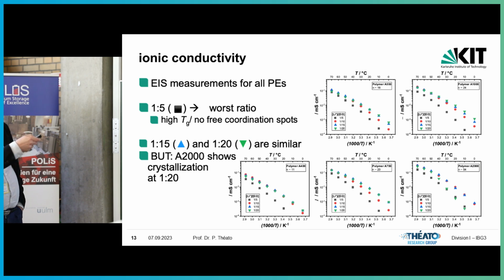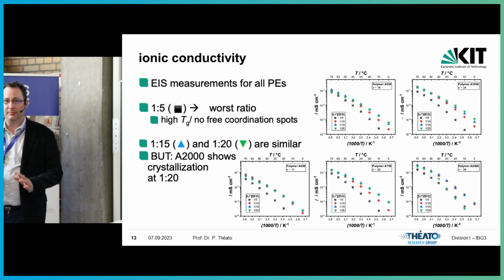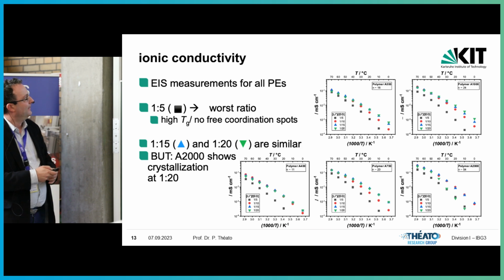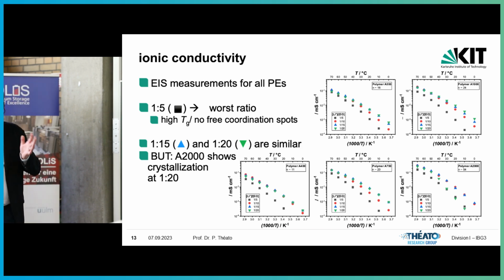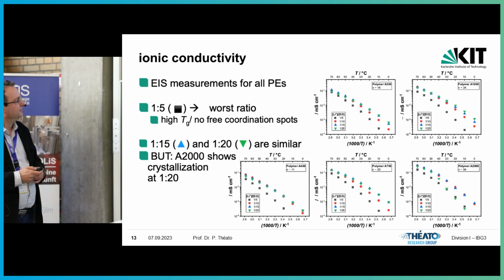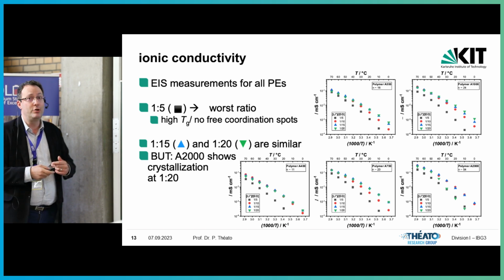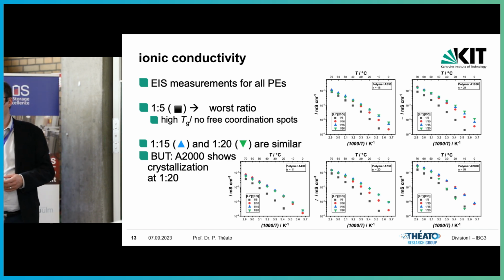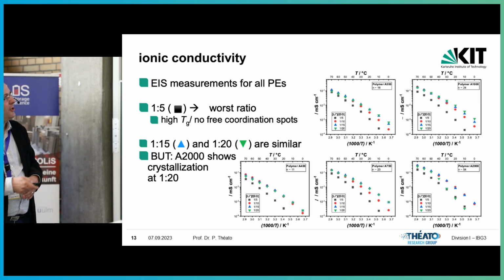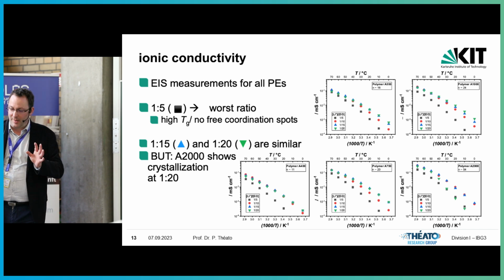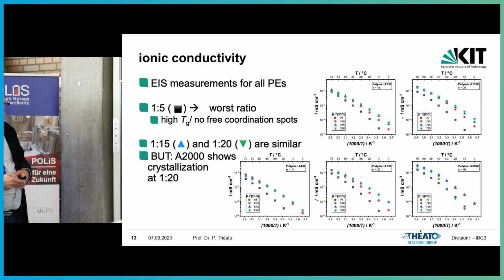So 1 to 5 is definitely the worst, no matter what side chain lengths you take. It becomes pretty obvious. 1 to 15 and 1 to 20 are very similar, so that here you can pick what you prefer. However, for the longest side chain at 1 to 20, you do see again that side chain crystallization kicks in. So that's also a limitation in here. So if you look at the data here, the green dots, you can see the deviation from the VTF curve behavior due to the crystallization. So this is something where quite some stuff is what we learned.